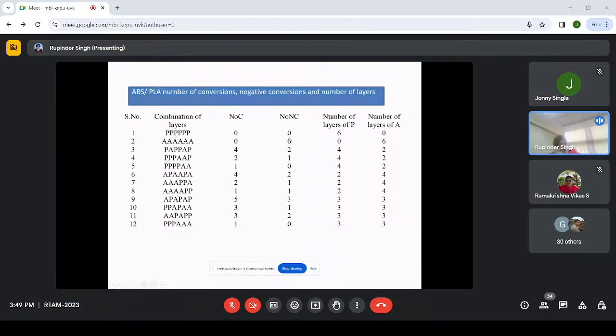Number of negative conversion is like if you are putting a material of high TG on the lower side and the lower TG on the upper side. So what will happen once you print like that? The material with a lower TG will have a side flow. That we actually observed once we put PLA on the ABS, because ABS has a higher TG as compared to PLA. So if you print the ABS first and then put the PLA, there is a side flow of material.